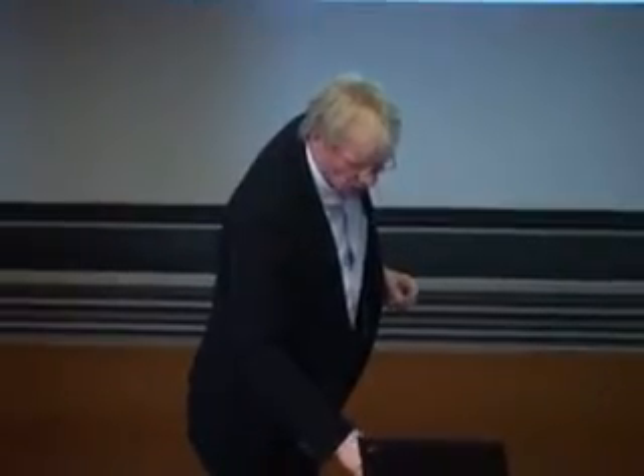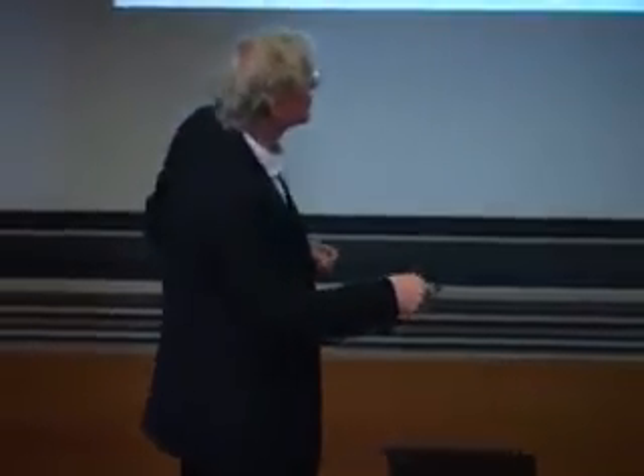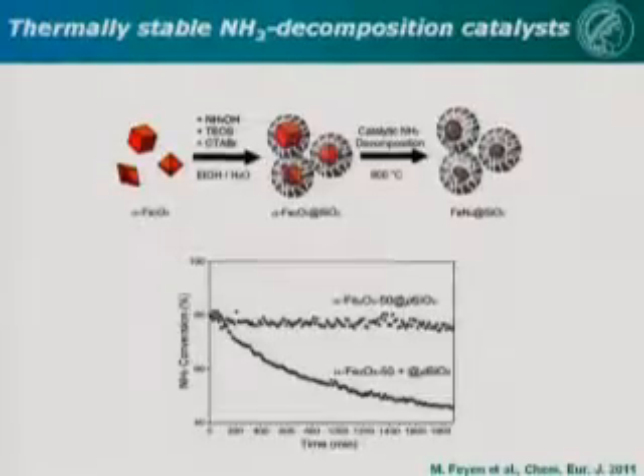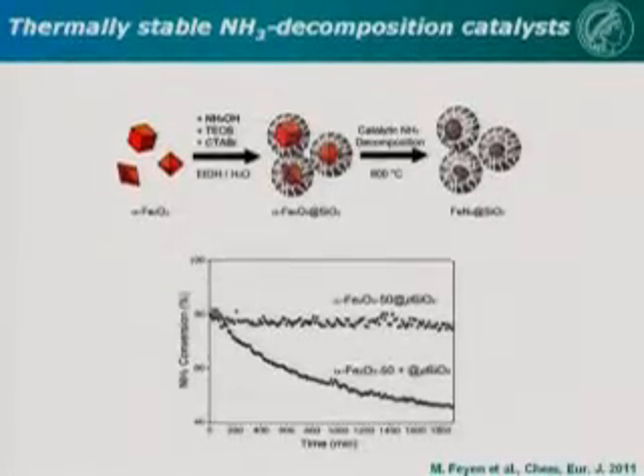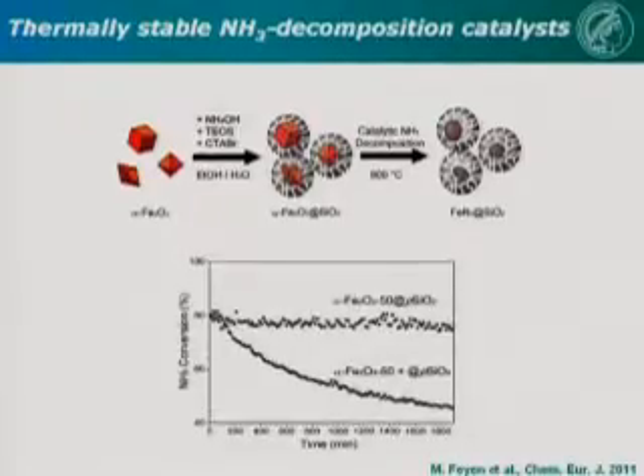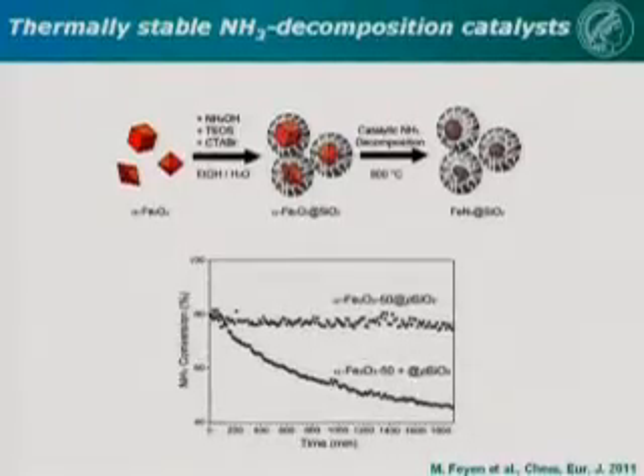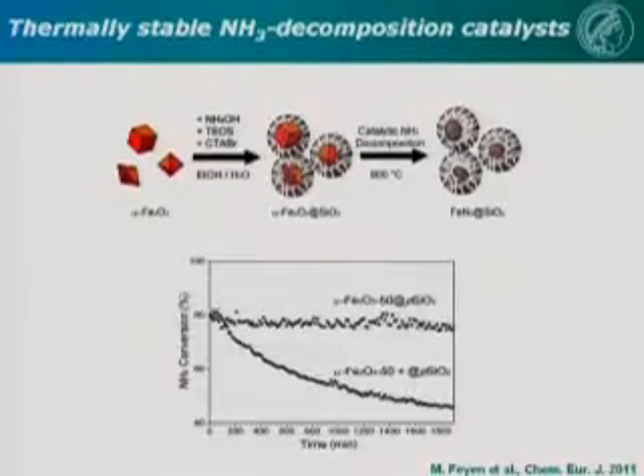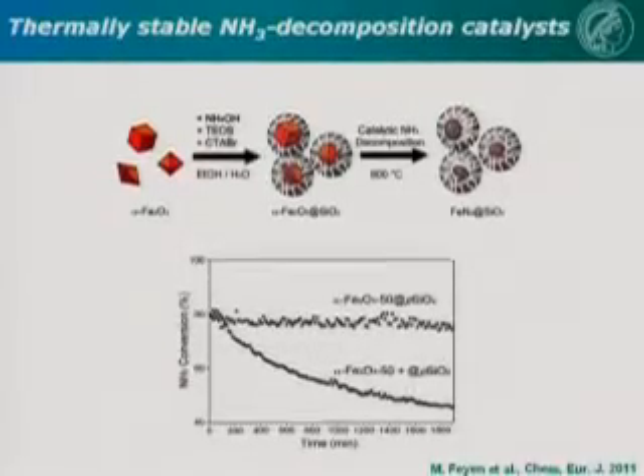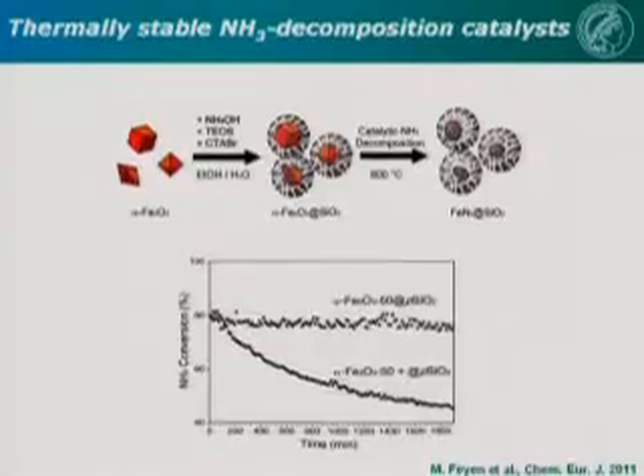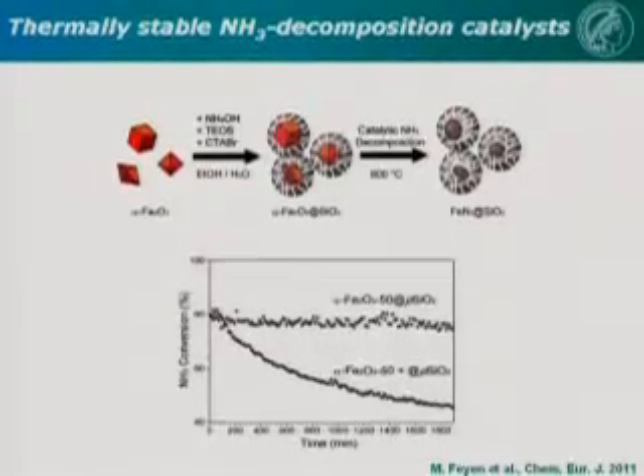And this is why I like this work, because Matthias Feyen, who did it, actually made a wonderful benchmark catalyst which allows you a direct comparison of the encapsulated and a reference catalyst. The encapsulated catalyst is stable over time here. This is something like 30 hours. The reference catalyst loses activity.